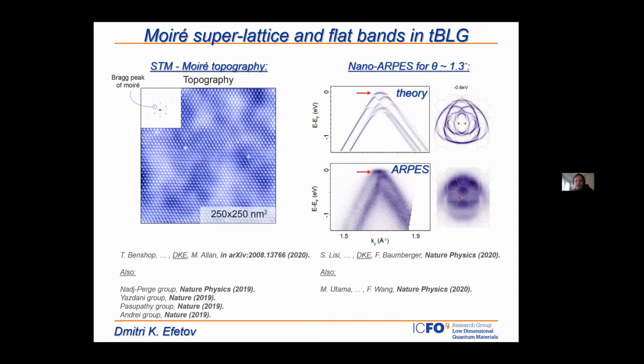which basically, the flatness of the bands results in an extremely high density of states. And the flatness of the band also makes the kinetic energy almost vanish, and because the electrons almost stop moving, interaction terms start dominating the whole structure.